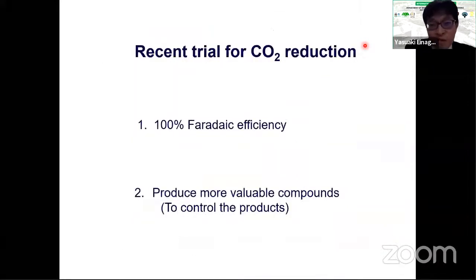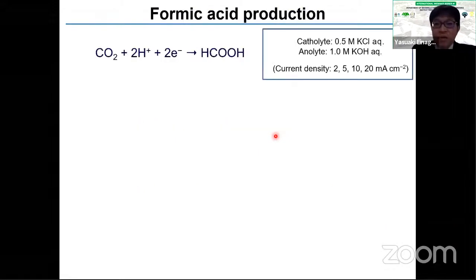So now I want to show the recent trials for the CO2 reduction. One direction is 100% Faraday efficiency. We studied many conditions, and finally, recently we achieved 100% Faraday efficiency by using this condition and this current density; we optimized the condition. Then CO2 to formic acid was very easy to obtain by using boron-doped diamond.